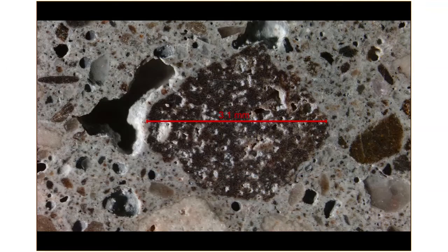Getting to the Portland cement. This is actually a Portland cement grain from the Buckeye Cement Company, and it's 3 millimeters, about 1/8 of an inch. That's how coarse this Portland cement is. In this image there's a lot of little black particles throughout the paste, the salt and pepper look to it. A lot of those particles are Portland cement, and you can see how coarsely ground this material is. We just didn't have the energy or technology back then to grind Portland cements fine. But again, this concrete's made 8,000 PSI in 100 years. It's produced dense concrete, and it's a city street that sees a ton of salt, and it's still surviving.